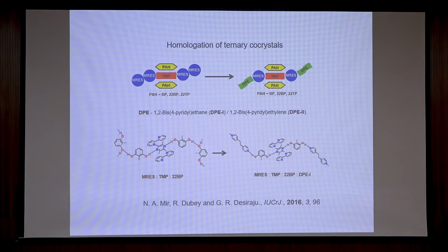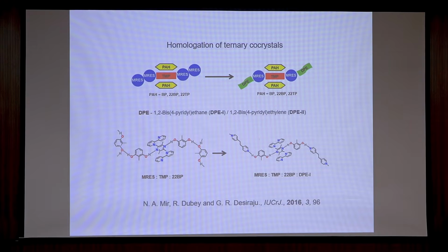Okay. Then we can exploit this difference. How? Once they are different, then we can put the 4th component. And once again it's a question of calibrating the interactions. The 4th should be strong enough that it comes in, but not so strong that it destroys the existing ternary and then forms something else new and unpredictable. So it has to be a very gentle graded addition of interactions.